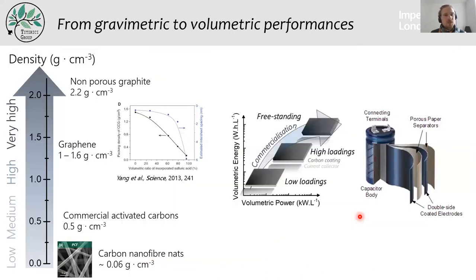And finally, before finishing, I'd like to present some work we've been doing to try to improve the density of these materials, because the problem of these carbon nanofiber mats is that they have densities below 0.1 gram per cubic centimeter. And commercial activated carbon are approximately at 0.5. And of course, 2.2 is pure graphite, non-porous graphite.